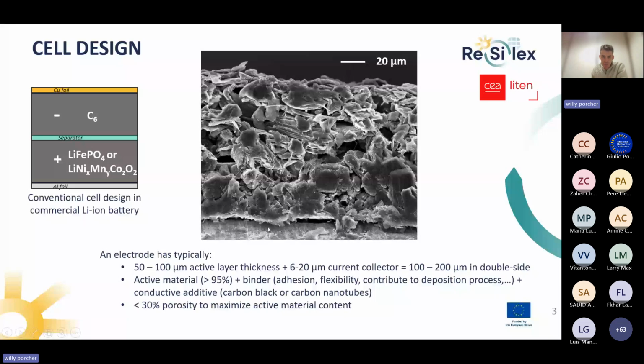And there is also some liquid inside for the exchange of lithium to the other electrode. So the idea is to really have the lowest proportions. It's what we call the porosity before filling of the electrode, and the porosity should be less than 30%.